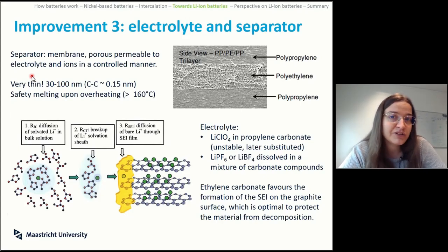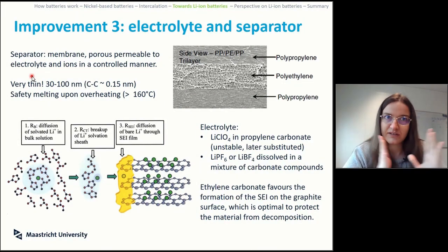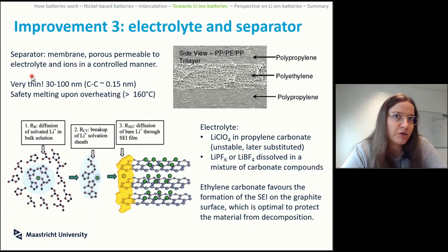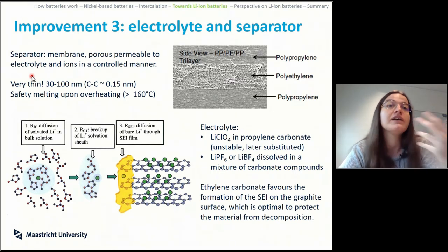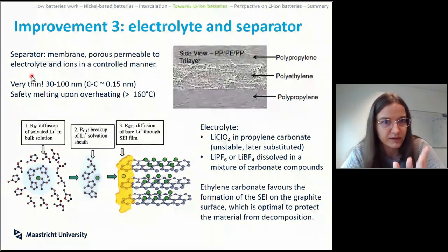And potentially this is your safety point against overheating, because since we want it porous, if you have a battery that is overheating and you melt the separator, it will basically stop the lithium plus from flowing. If you stop the lithium plus from flowing, then your battery stops working. So fine, nice. You have a fail-safe: if the battery is overheating, it will not keep overheating, because you stop the electrochemical reaction and you put it back at the equilibrium where it was at that level.